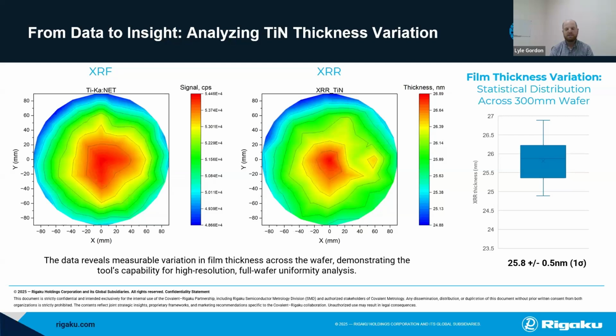So even so we could see that really significant change in fringe frequency, it's actually a variation only about plus or minus half a nanometer across that full wafer. So we have really good ability to both map it and to have sensitivity to small changes in film thickness. And in this case, for a film that's strongly absorbing to light.